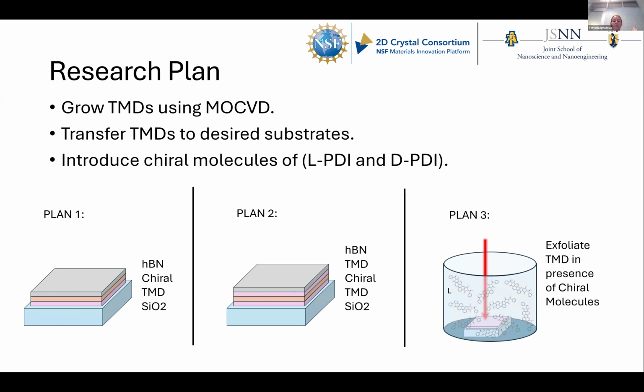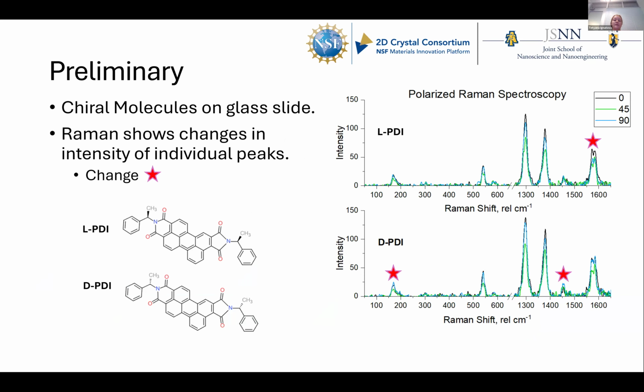Plan one included putting the chiral molecules on top of the TMDs and then studying that structure, maybe adding a layer of hBN, I don't know. And then the second plan was to intercalate the chiral molecules in two layers of TMDs. This could be the same, like two layers of MoS2, or alternating MoS2 and WS2, or either or, and then to liquid exfoliate them. Before I went to PSU, I deposited my chiral molecules onto a glass slide and studied the polarized Raman spectroscopy of them. We had changes in intensities and very slight shifts when changing the polarization of the two chiral molecules, L and D PDI.